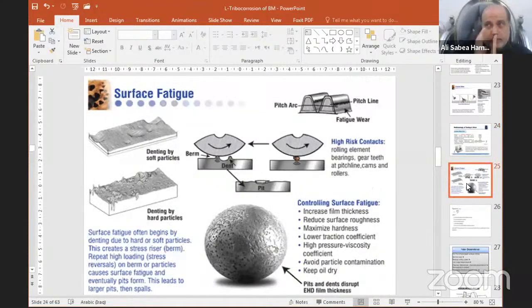Surface fatigue occurs with repeated loading at the surface. Surface fatigue often begins with hard or soft particles. It can be controlled by increasing film thickness and reducing surface roughness. Reducing surface roughness is very important for surface fatigue. Maximize hardness and lower the traction coefficient. High pressure viscosity coefficient. Avoid particle contamination. Keep oil dry. This controls surface fatigue. Increasing film thickness and reducing surface roughness are very important.